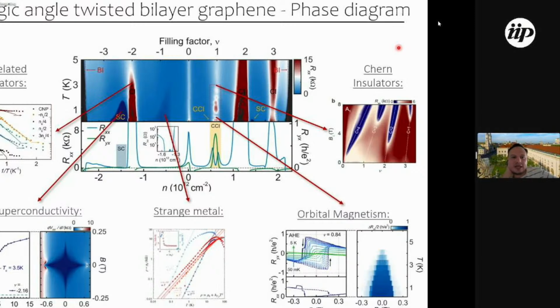And really, to summarize, what I want to emphasize is that this measurement was taken on one single device, a homogeneous device where, by applying a little voltage to the backgate, you can tune from one phase to another repeatedly without any degradation of the device. You can study transitions between the phases continuously without changing the device. And by applying a little bit of a magnetic field, you can also get all these orbital magnets and Chern insulator states.